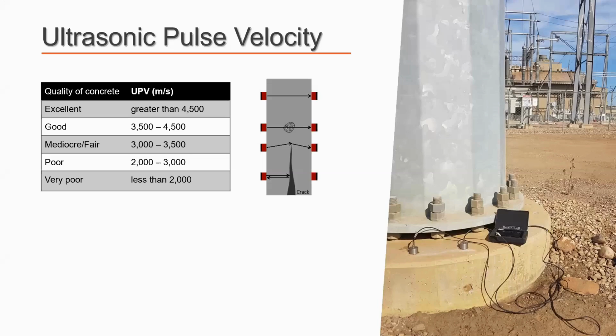There is a table in this one, and on the right side, I'm showing you the same UPV device in another setup. You see there are two probes again, but we can do ultrasonic pulse velocity in three different ways. One is direct, when the two probes are facing each other. This is more for laboratory conditions when you have access to both sides of the concrete. If you don't, and you are testing concrete elements like this one, and you have access only to one side of the element most of the time, or two sides in an edge element, then you have to go with semi-direct or indirect methods. But in general, the better the quality of concrete, the higher the wave speed will be.